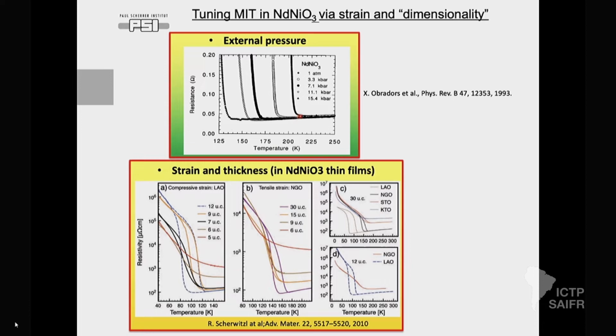And when you are applying the pressure, you go to, let's say, 15 kilobars, you are going already below 150 Kelvin of the metal insulator transition. So this is not so big pressure; that was actually a paper in 93. Now you can go in with even much higher pressure in these pressure cells. However, there is another way, because there is internal pressure. So there is always strain, or say pressure, that you can apply also semi-intrinsically.